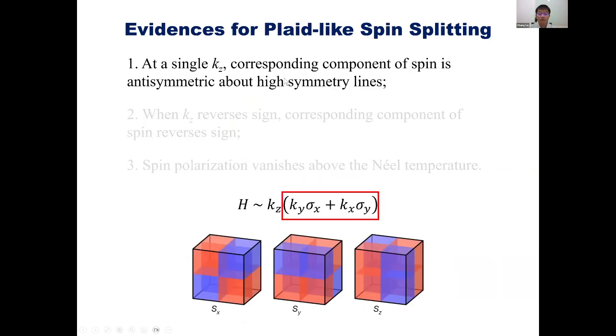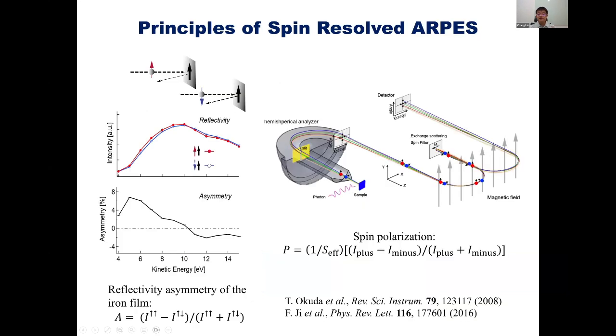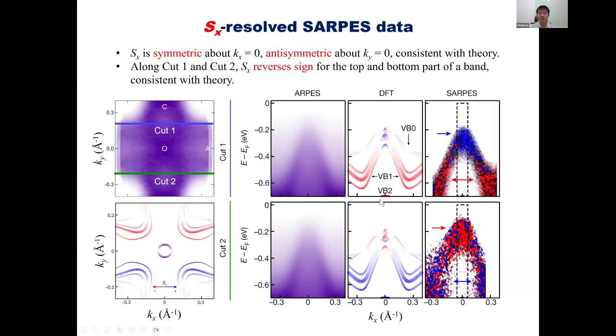And we collect three types of evidence for the plaid-like spin splitting in this compound. First of all, at a single kz, the corresponding components of spin are antisymmetric about the high symmetry lines. This corresponds to this part of the effective Hamiltonian, which is exactly the same as the Dresselhaus-type spin splitting. So we need to confirm that the in-plane spin texture is Dresselhaus-like instead of Rashba-like. These are the details about our spin detection. We will skip that, and this is our data.